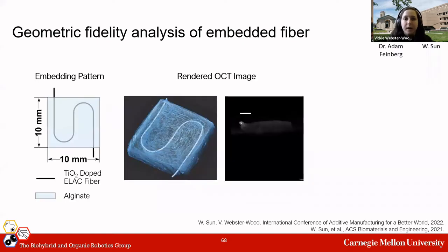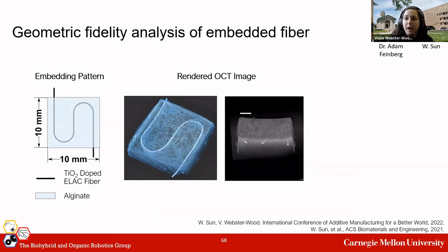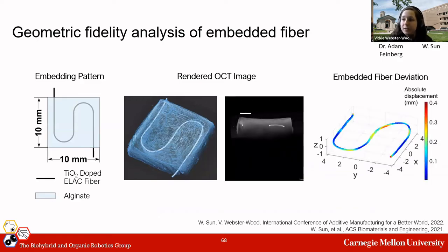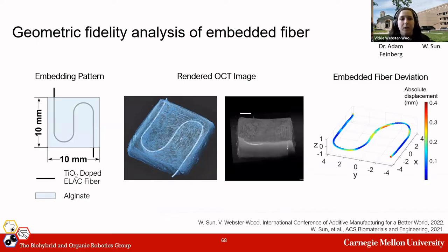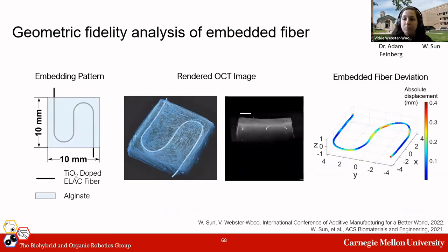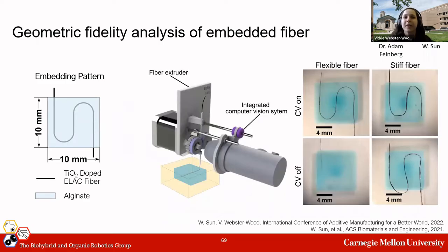When fibers within that green printability region are printed, we can fully encapsulate them within the hydrogel. And we see sub-millimeter deviations from our desired print paths in our initial prints. More recently, Wen has also demonstrated that we can improve print fidelity using a closed loop computer vision based feedback control process.